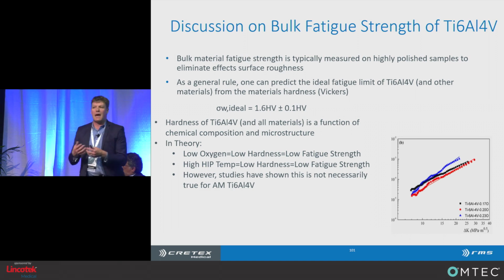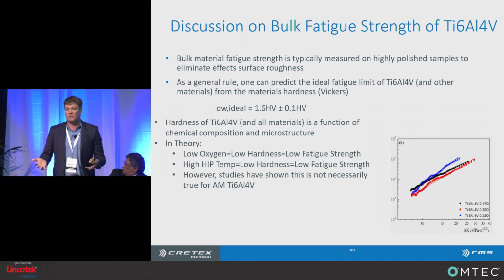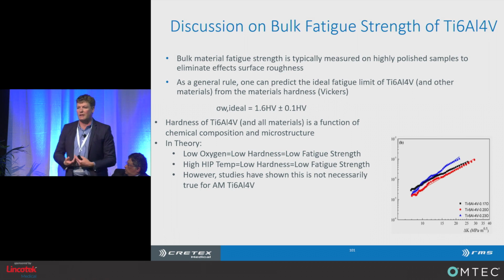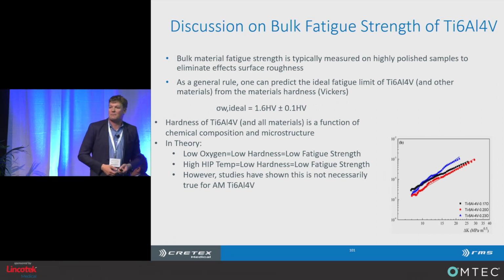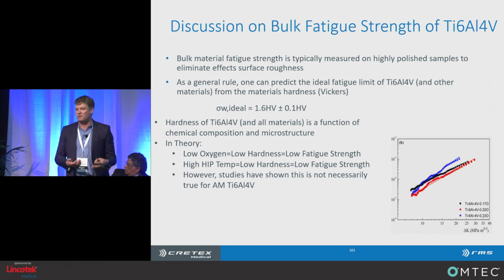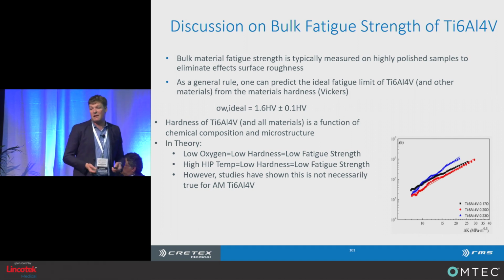So just because we have these rules of thumb for wrought and cast materials that we're used to, they don't necessarily correlate to additively manufactured Ti-6Al-4V. And that's typically because we have a pretty unique microstructure coming out of our additively manufactured process, right?